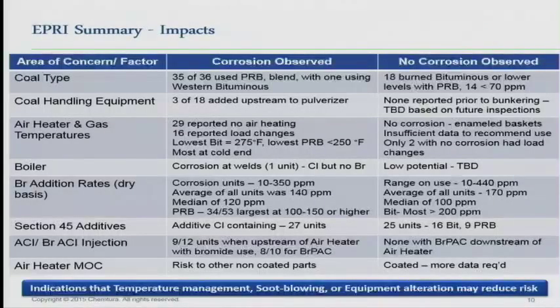Where they did not see corrosion, they had enameled baskets, which are showing to be pretty reliable as far as corrosion resistance, although they would like to see some more data. And there were only 2 that did not have corrosion that reported any kind of load changes. So again, these are plants that are running a little more flat out. You don't have the up or down disruptions. In the boiler, 1 unit showed some corrosion, but again, that showed chloride and no bromide present at that point. And when you look at no corrosion, you wouldn't really anticipate, given those conditions, to be seeing it.